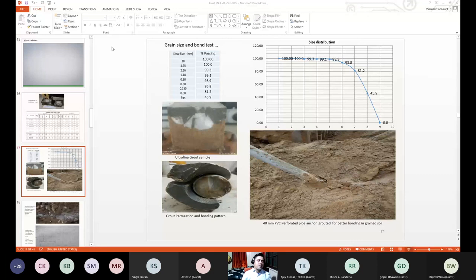And the results were in the Pir Panjal tunnel, you can say the 50 MPa we have seen on cement grout. The water cement ratio, if you control it at 0.5 to 0.6, 0.7, it will be good. And if more than 0.8, it will reduce your strength. Admixture will give you the workability and the flow, but later on the shrinkage and the proper strength will not be achieved if your water cement ratio is higher.